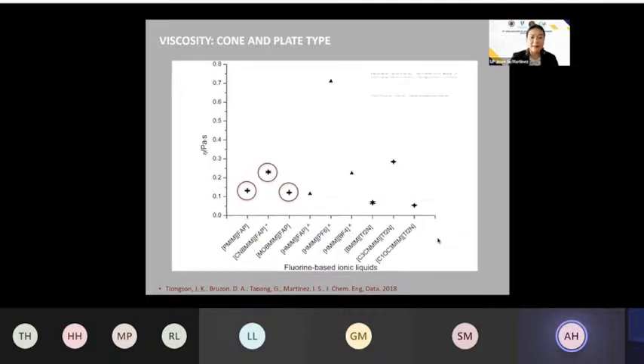And comparing, of course, the viscosity of our ionic liquids to other ionic liquids out there, you can see here that they have comparable values. And then we also think that because we use a large anion, which is a FAP anion, it actually has higher free volume, which lowers, of course, the viscosity. And then there's lower ion interaction, possibly between the cation and anion, and a higher mass transfer rate.